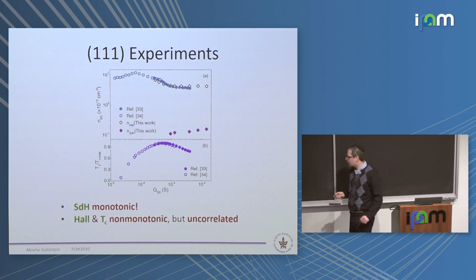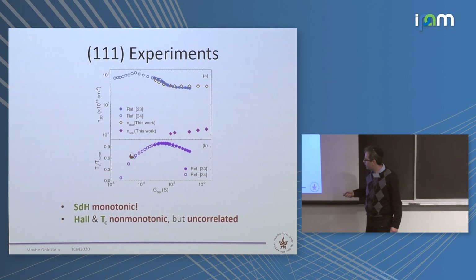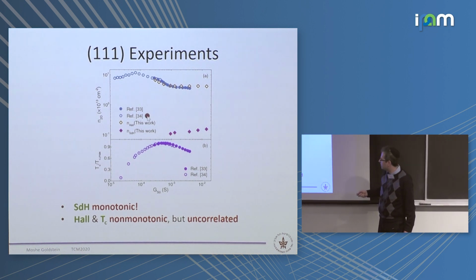And this is what my colleagues did. They went and did the same kind of measurements on 111. And what they found is that this is Shubnikov, this is Hall density, this is Shubnikov density. There is still this big difference between them, but now Shubnikov is monotonic. Hall is not monotonic, it has a peak here.